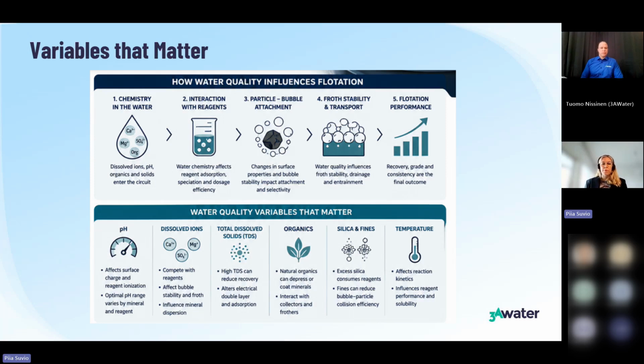Then if we look at the individual water quality variables that matter the most, we have first and foremost the pH. So we have the pH window, which often governs where the best flotation performance is in the process. Then we have certain dissolved ions that are causing issues. In particular calcium and magnesium, which are hardness-inducing ions, and then we have the sulfate. The amount of total dissolved solids is an issue. These directly reduce the recovery. Then we have organics, which can cause certain issues. They can depress or coat the minerals, for example.